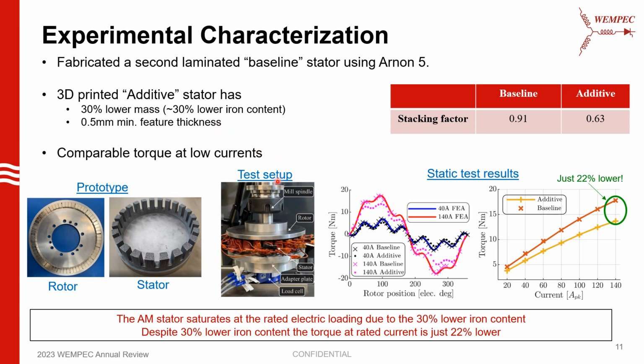The test setup to characterize these stators is a CNC mill, which is repurposed as a dynamometer. The rotor of the machine, which is the same for both the additive and the baseline machines, is fixed to the mill spindle, while the stator is mounted on a load cell fixed to the mill table. The load cell allows measuring reaction torque on the stator. At different rotor positions set using the mill spindle control, rated Q-axis currents were applied and the torque on the load cell was measured. The static test results are shown here.